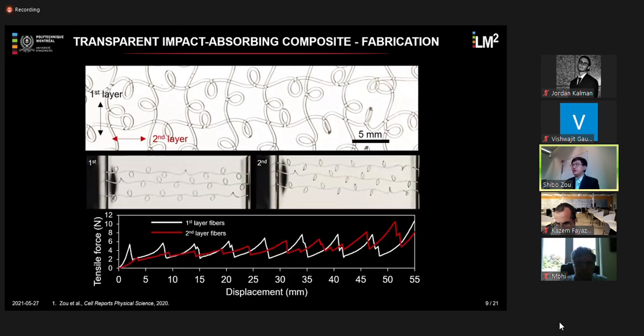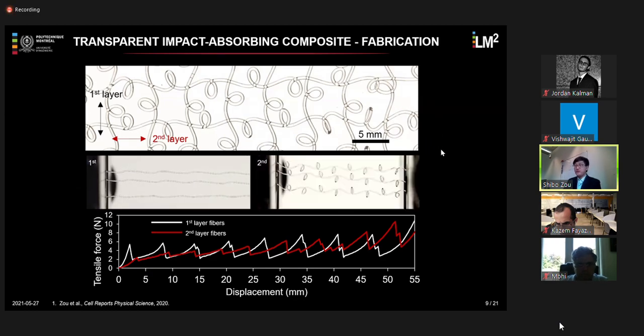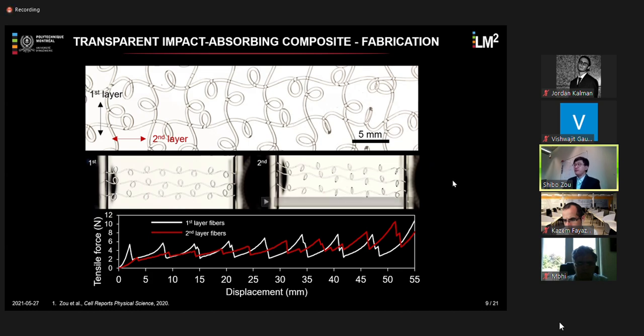And we found that the mechanical properties of the fibers from the two layers are pretty similar with each other, except that the bond strength on the second layer is a little bit less than the first layer, but the general behavior is similar. And all the sacrificial bonds are all functional in both layers.